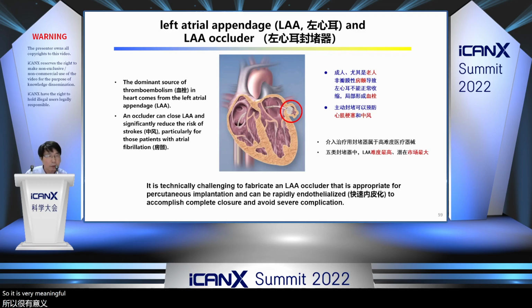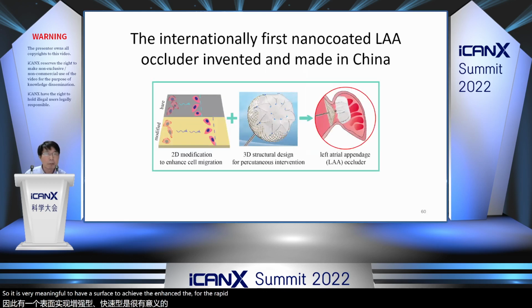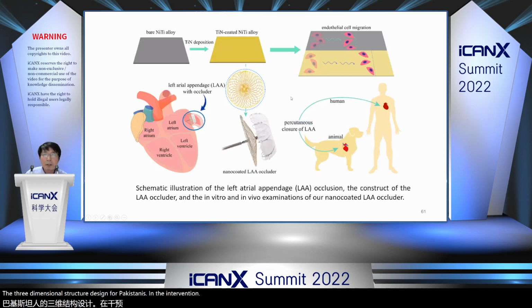So it is very meaningful to have a surface that achieves rapid cell migration. Here is the basic idea of our invention, and it's the internationally first nano-coated LAA occluder invented and made in China. We made the two-dimensional modification to enhance cell migration and the three-dimensional structural design for percutaneous intervention. Now, we started from a super elastic metal. It has been much used in the clinic. And we use some bioceramics to modify the metal to avoid the nickel ion release.